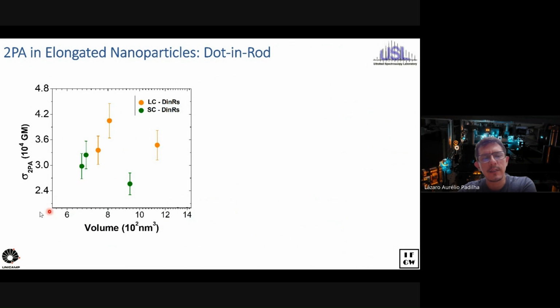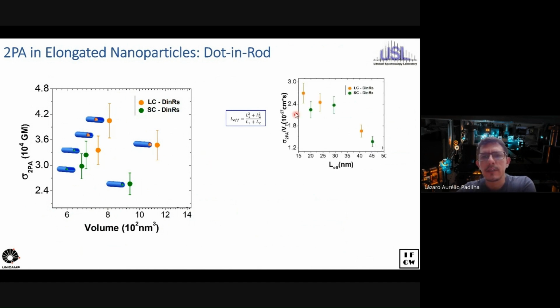We have done these studies, and we've seen that apparently they split into two different behaviors, one volume dependence here and another one right there. The difference between these samples here and these samples there is basically that here the quantum dots are near the center of the nanorod, and these ones are on the tip. To rationalize this, what we believe is that when you're in the tip, the quantum dot is farther from the total volume of the nanorod, in the sense that we can define this effective length, like the two lengths squared divided by the total length. And we see that the longer the effective length, the smaller is the volume normalized two-photon absorption cross-section.